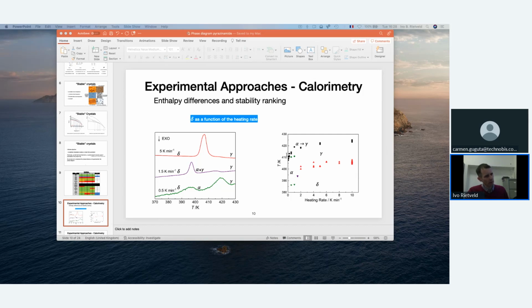I also plotted, but these are different measurements, alpha turning into gamma, where you can see that in particular delta behaves differently because it turns immediately to gamma over here. Whereas if you go very slowly, then you see that the system actually falls back to this alpha-gamma system. What you also see is that as a function of the temperature, these transitions are going lower and lower, and it's actually very difficult to put a finger on where the actual transition temperature or the equilibrium temperature is.